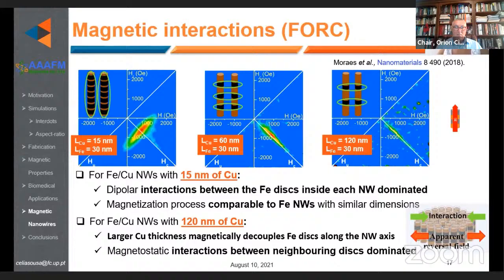So, to evaluate the interaction between these nanowires, we also performed the FORC analysis, and as we can see here, for a lower separation between the iron nanodiscs, we see behavior that is dominated by the dipolar interactions between the iron nanodiscs, and the iron nanodiscs have a behavior like continuous nanowires without the copper layers. When we increase the copper layer, we see the individual behavior of these iron nanodiscs.